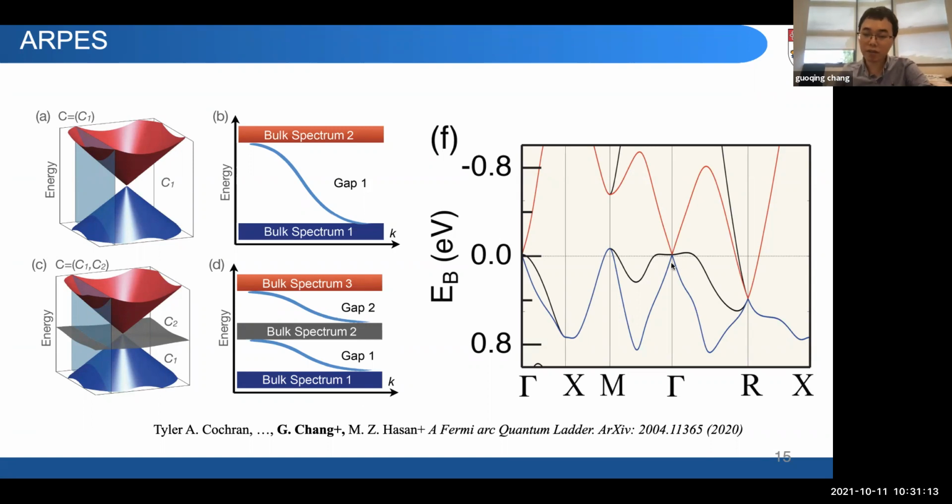So let's look again at the band structure here. You can see this R point is below the Fermi level. However, the splitting here is very small, so within the experimental resolution we cannot directly visualize this multifold crossing. The separation at the gamma point is large enough. However, if you look at the Fermi level, these crossings are actually slightly above the Fermi level. So the R path can only see the states below the Fermi level. Also, this sample is slightly hole doped, which will push this node further away from the Fermi level. That is why people didn't directly see the crossings there.